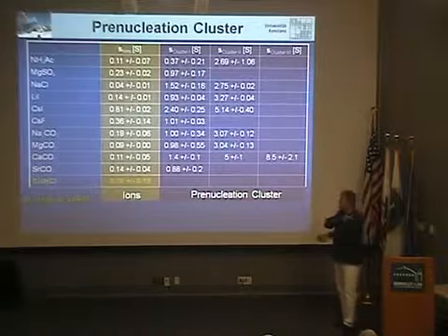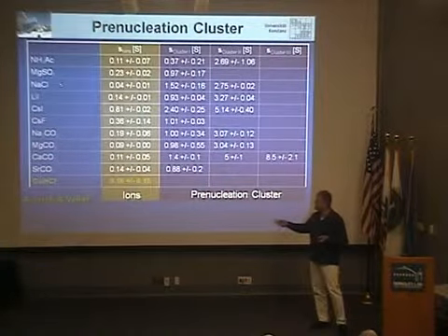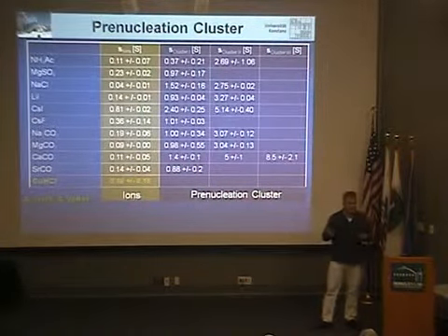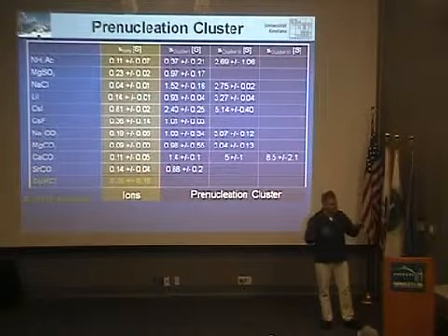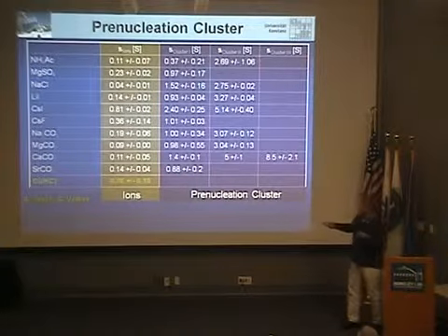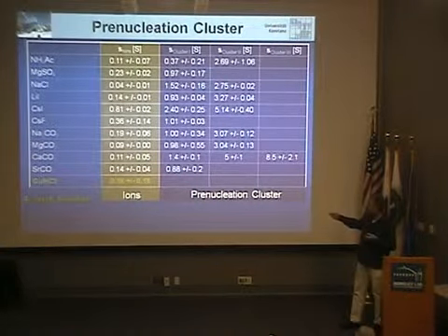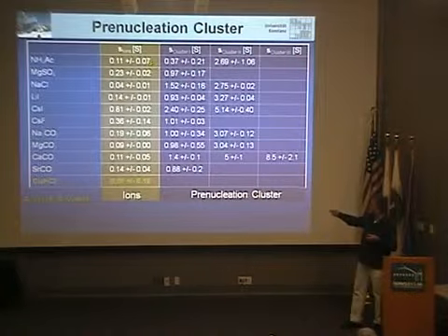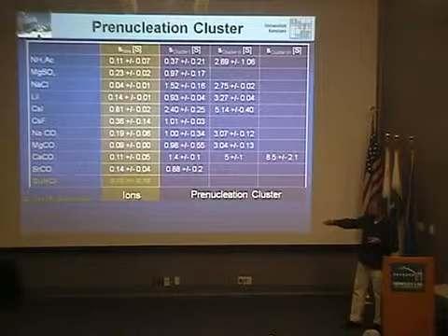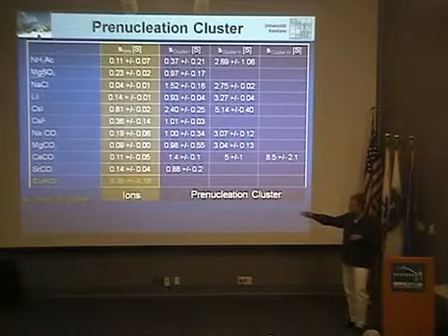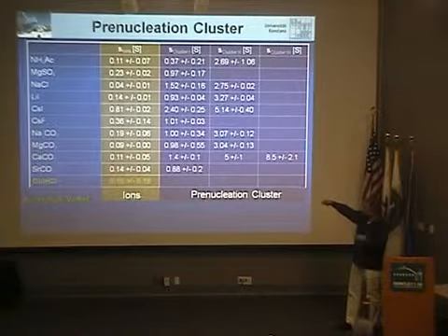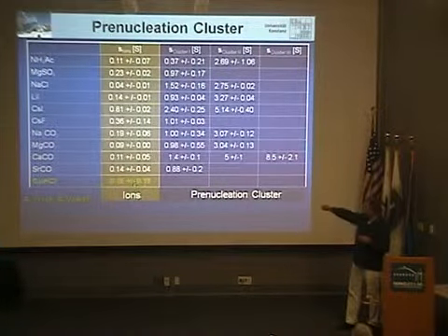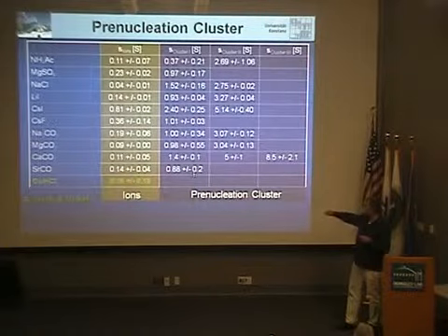But we did a few further experiments. First we started to look at sodium chloride in the analytical ultracentrifuge because we wanted to have a system which does not form clusters to compare it. But then we were quite astonished, and we saw, you see here the columns, that sodium chloride also forms clusters and cluster aggregates. And you have here a whole bunch of different salts. You have soluble salts, you have very sparingly soluble salts, and I don't want to go through them, but you see that they all show ions in the analytical ultracentrifuge, and they show clusters.